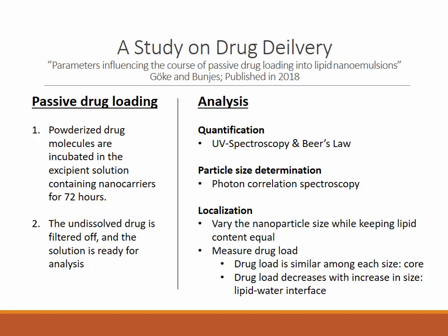First, they passively loaded the drug into the nanocarriers by incubating and mixing for 72 hours, guarded from light. And after that time passed, they filtered off any undissolved molecules so that they had just a solution of the drug-loaded nanocarriers. Next, the amount of drug loaded is determined through ultraviolet spectroscopy.